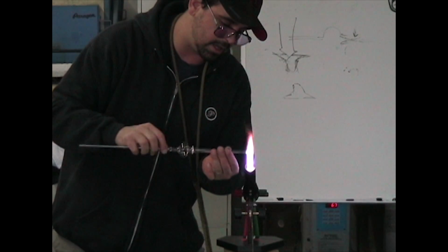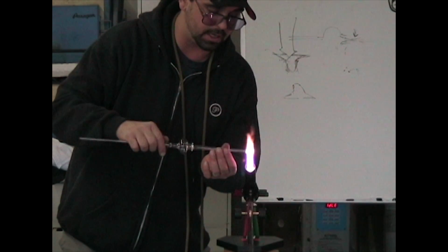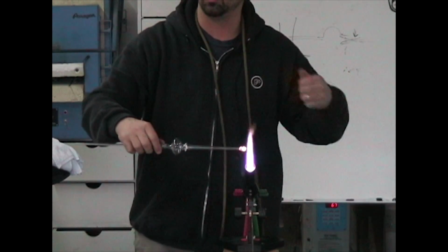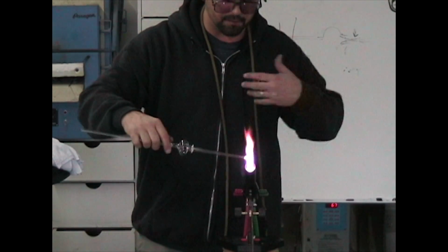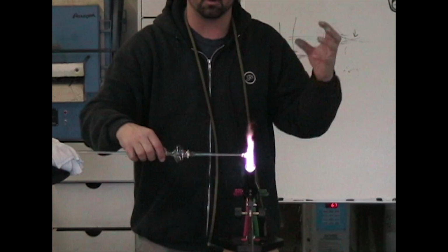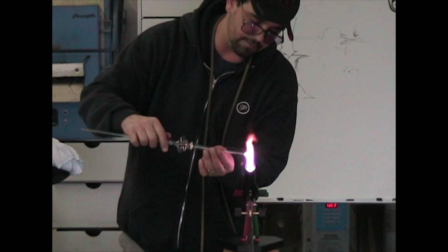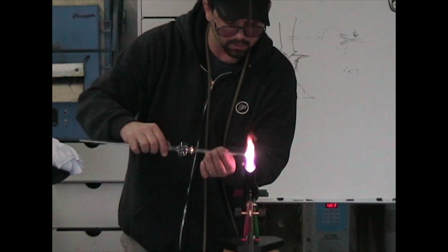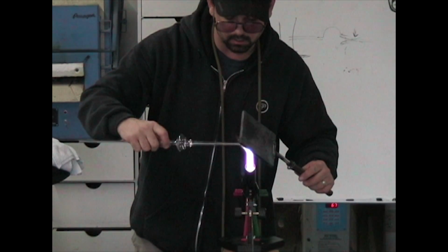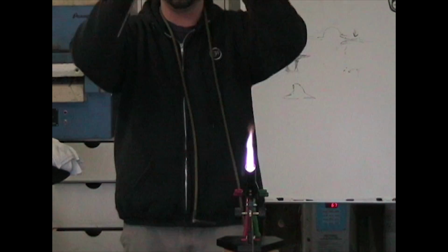Now for me, doing it this way gives me the opportunity to make sure that I get the glass all the way fused, the color all the way fused to the clear in this case. Sometimes if you just take a rod and put it on the end and hope you get it really well fused, I get the acute angles, and maybe I'll even catch air bubbles in the way that the rod will fold over into the piece that you're attaching it to. I found to get around that, if I just put a little gather on there and let it melt all the way in, when I go back and paddle it a little bit, it widens it out, and it just continues that footprint of the heat that was put down from the gather growing into it.